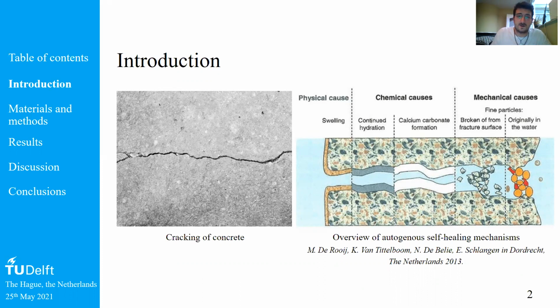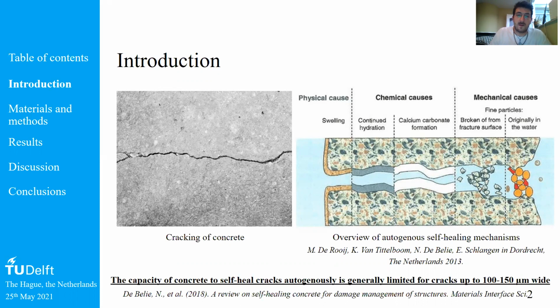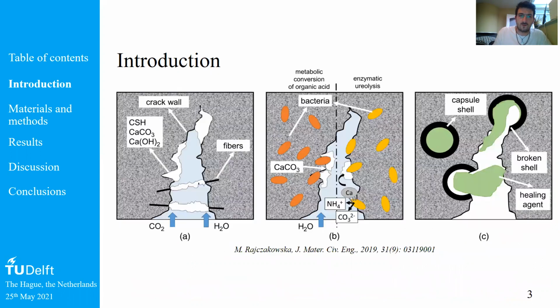The thing is that during the last 10 to 15 to 20 years of research, the scientific community determined the maximum healable crack width that concrete is able to self-heal, that is around, in general, 100 to 150 micrometers, of course, depending on many interrelated parameters related to the mixture. Therefore, since self-healing of concrete might theoretically improve a lot the service life of our infrastructures, a lot of